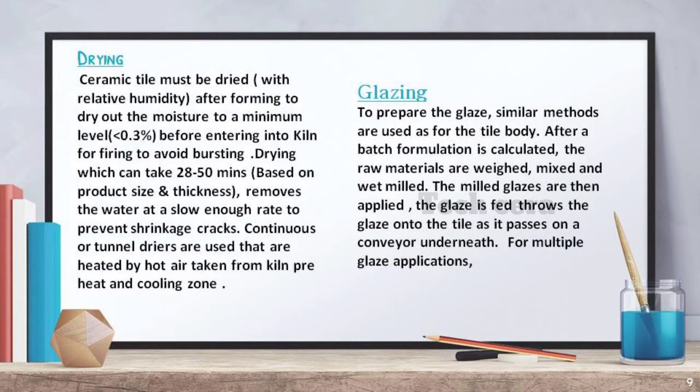Drying. Ceramic tiles must be dried to a minimum moisture level of 0.3% before entering the firing, to avoid bursting.